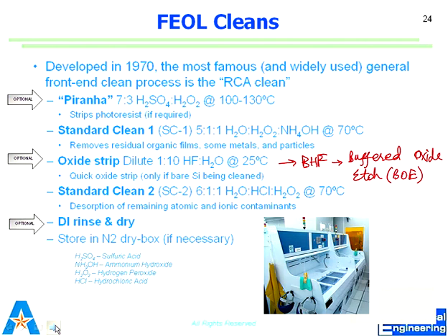Right? So, of course, it's going to neutralize, essentially, when the whole hydrogen peroxide is used up, but you have much more sulfuric acid to do that reaction. So you have much more sulfuric acid that doesn't react, but the whole reaction is very aggressive, much more aggressive. So the standard is what the book says, 7-to-3. We use 1-to-1, 1-to-2, 1-to-3, many different ratios. Now I see what you're saying. I was thinking the other way around. I was thinking first hydrogen peroxide and then sulfuric acid. So, yes, here it's almost double. 3-to-6 would be 1-to-2, so it's 7-to-3. Sorry about flipping the order here.